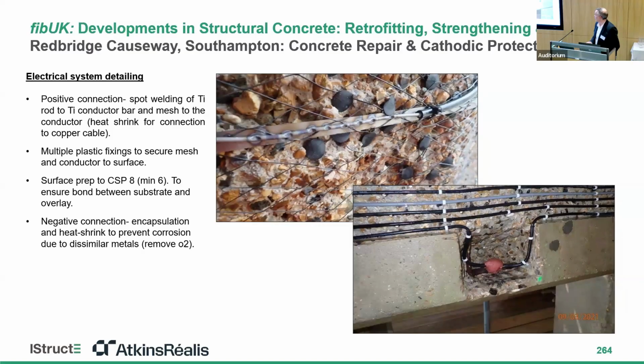A couple of details here. The top one is a positive connection, and the bottom one is a negative connection. The positive connection involves the spot welding of a titanium rod to the titanium conductor, and also the mesh to the conductor bar, which you can't really see in that picture. And then the black cable coming in is actually heat shrink, which is connecting the copper cable to the titanium rod. It's vital that it is airtight, and the heat shrink used is adhesive lined to prevent oxygen from getting in. And then the negative connection at the bottom is a similar thing, but there's a welded stud on the bar that's beneath that blob of epoxy. And then the copper cable connecting on either side is again heat shrunk to prevent oxygen getting in and causing corrosion because of dissimilar metals.